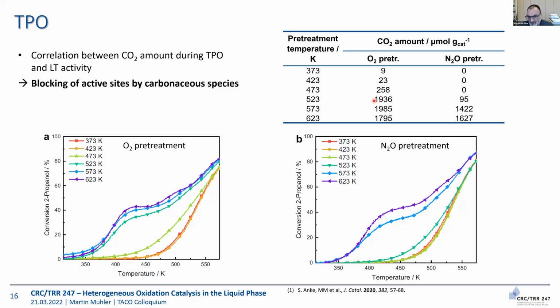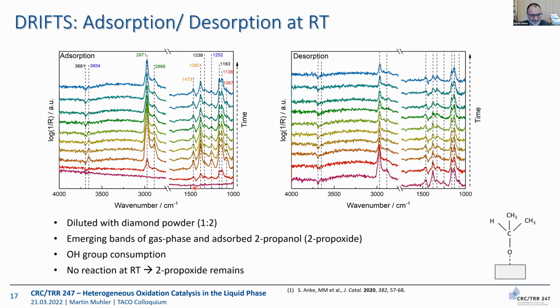Yeah, and then we integrate the amount of CO2 formed, and then we see immediately, as soon as we start burning of coke as CO2, then we regenerate this low temperature pathway, and in oxygen that starts earlier. So we have already, after regeneration at lower temperatures, the low temperature channel back. One minor comment: you see here that this low temperature channel seems to consist of two channels, and I'm coming back to that later.